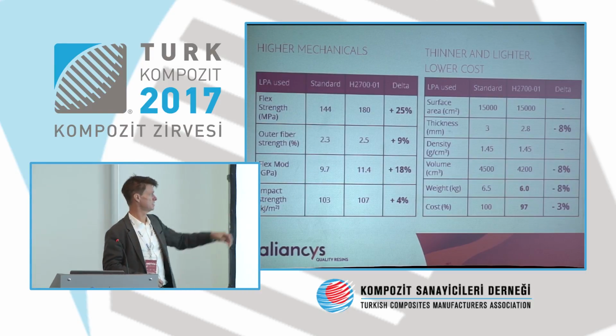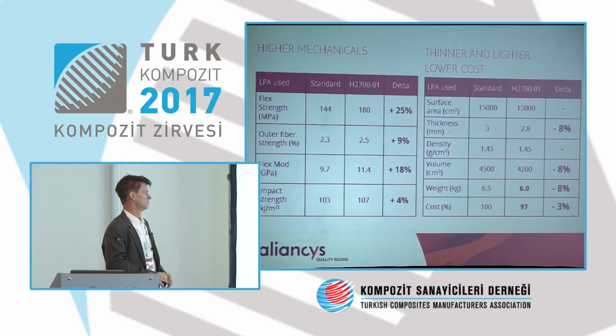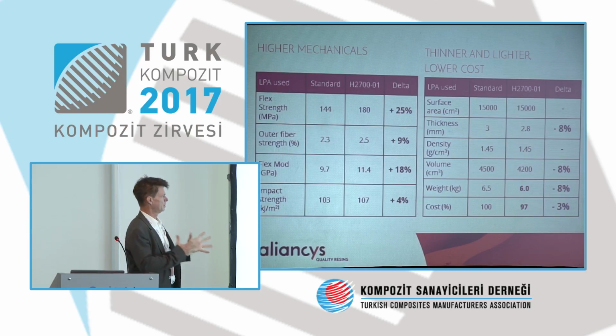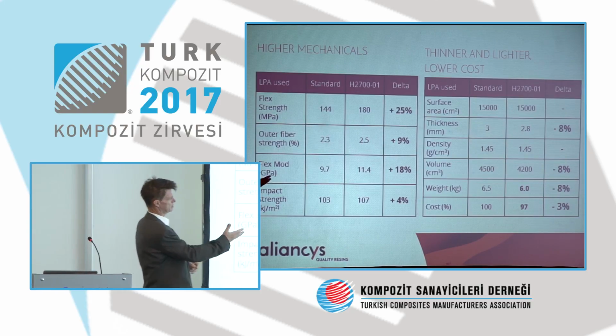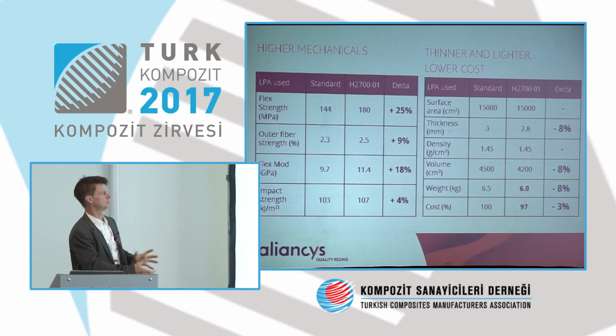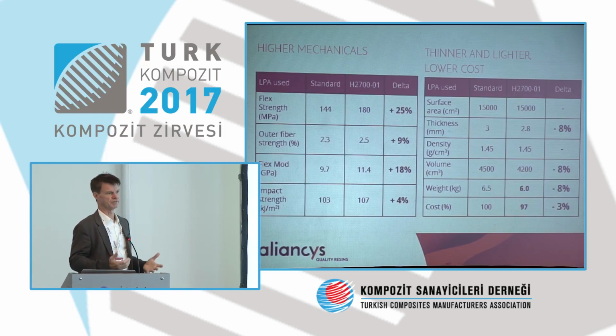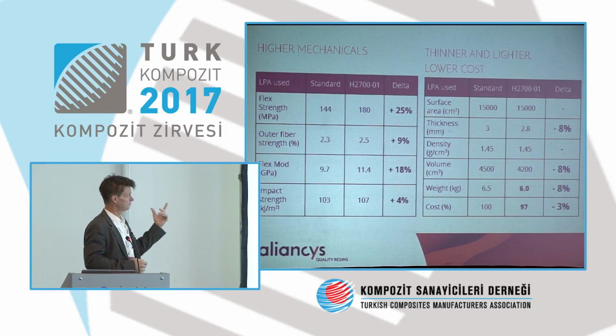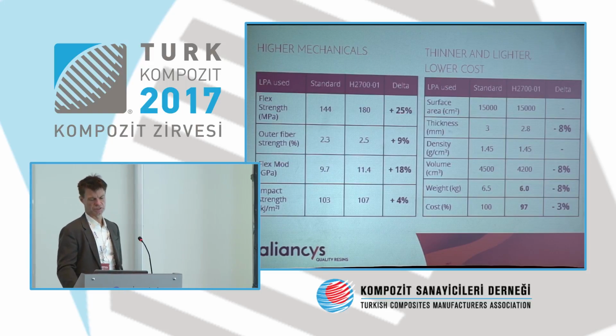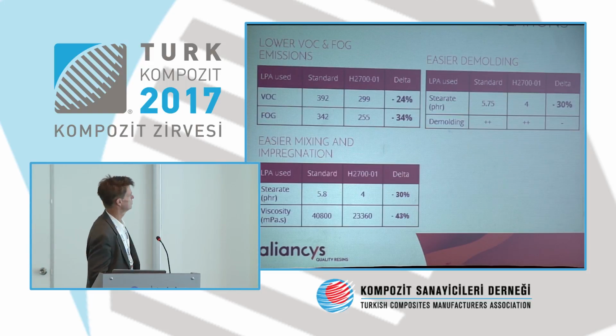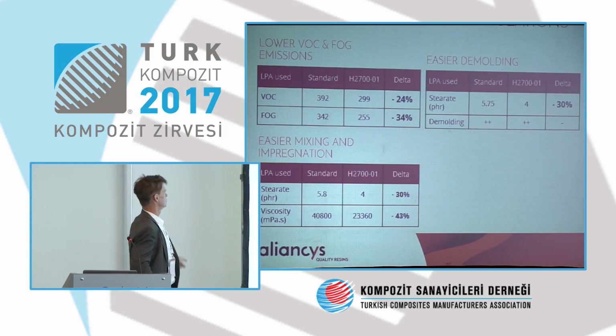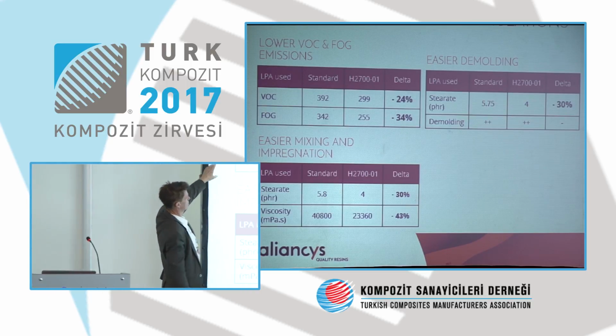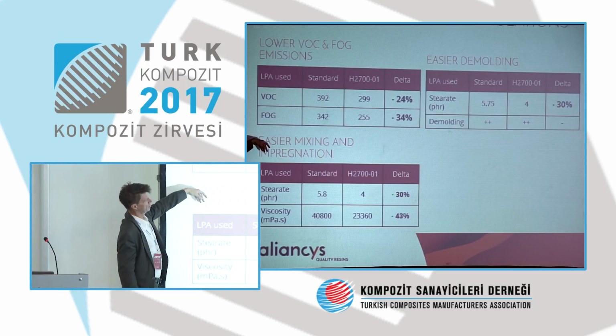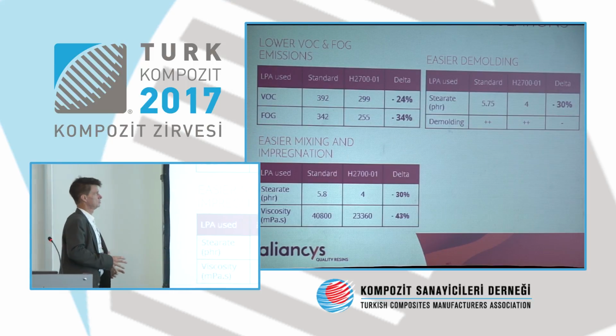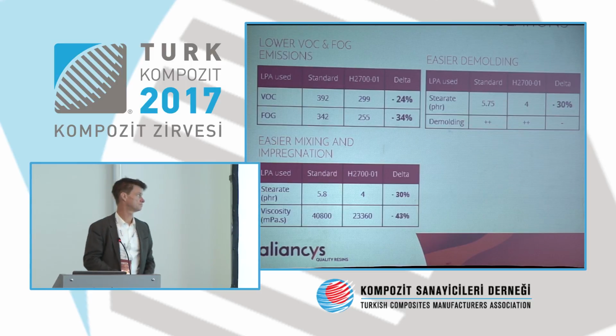So the density is basically similar. And the weight basically is then lower. So all in all, there's a cost saving. What we also did find is you have better release performance. That's also visible here. So we did find other advantages. We checked the VOC and the FOG, and we could find lower values compared to a standard Class A system.